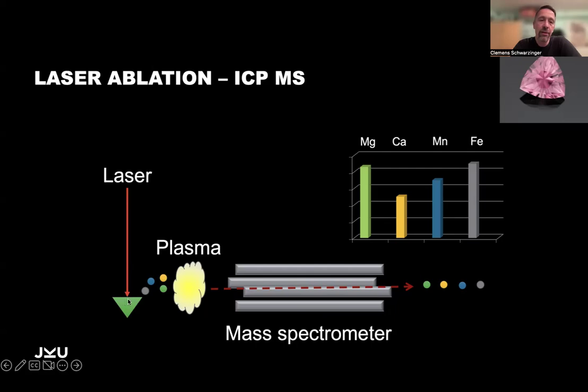So the material that is shot out of the garnet surface, we transport into the plasma. The plasma is something like our sun. It has temperatures of about 10,000 Kelvin, 10,000 degrees centigrade. It's pretty much the same at these temperatures. And everything disintegrates into ions and atoms. And the ions can then, in a mass spectrometer, be separated. We separate them by their mass, like the periodic table, they're listed in the masses, and then they're detected.